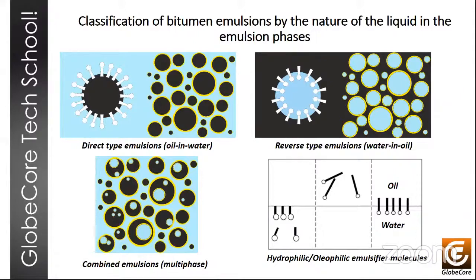With small amounts of emulsifier, we get an inverse water in oil emulsion. As we increase the concentration of the emulsifier, we reach a certain limit, and when we step over that limit, we get an oil in water emulsion. With a further increase in the concentration of the emulsifier, the dispersion of the emulsion increases, reaching its limit at a certain ratio again, after which an inverse emulsion forms again. Next slide, please.